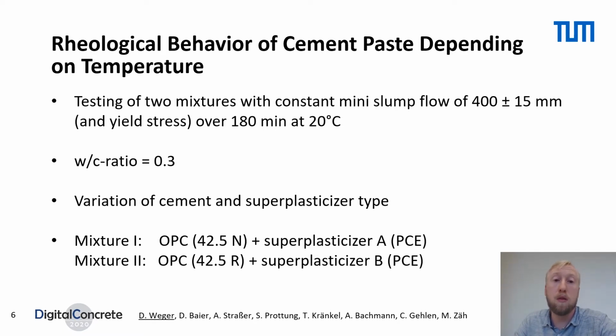In this first experiment, two very fluid mixtures with a mini slump flow of about 400 millimeters were tested. The water-cement ratio of the mixtures was fixed to 0.3, and for the measurements, two mixtures were produced with varying cement and superplasticizer type. There, mixture 1 consisted of a normal OPC, and mixture 2 was made of a rapid OPC. And comparing the two superplasticizers, superplasticizer A should show a slow adsorption behavior and liquefaction over time, whereas superplasticizer B should adsorb faster but with decreasing effectivity over time.